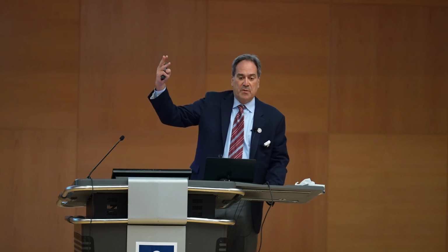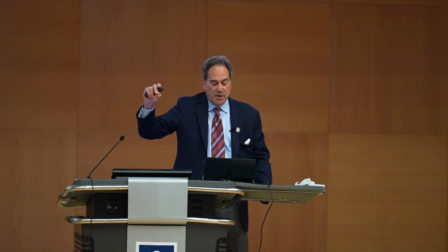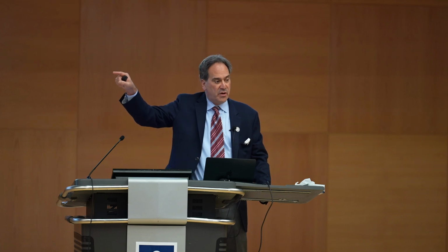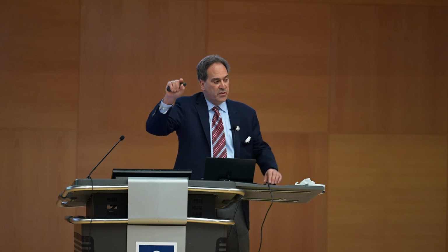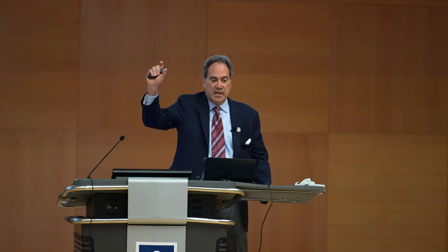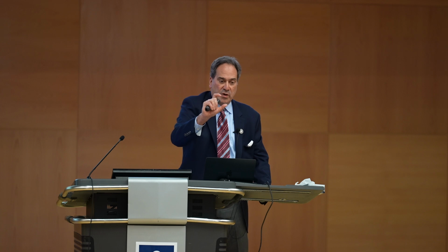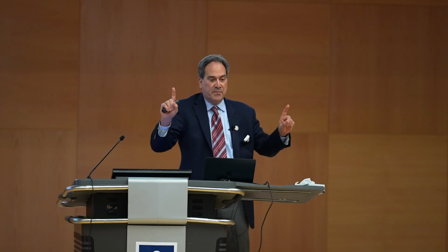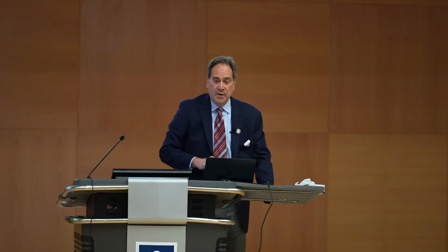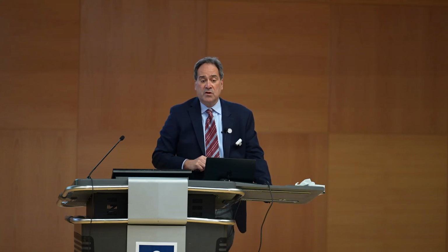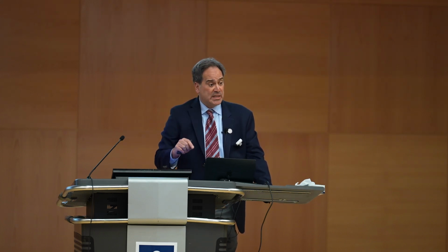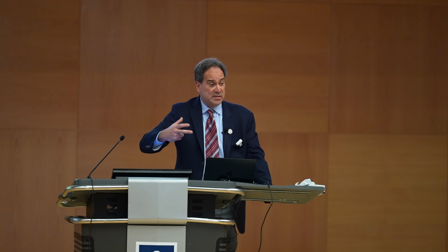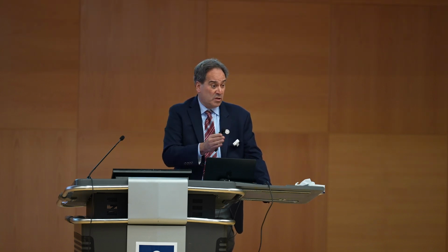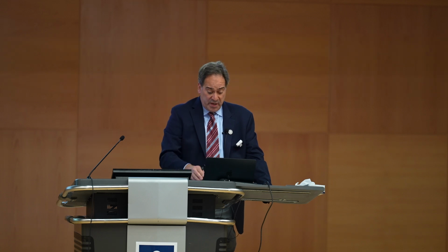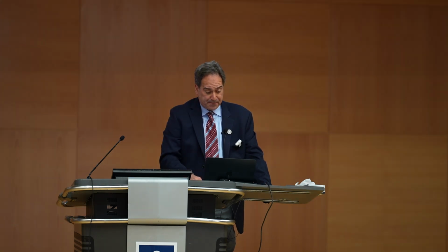These now are 3-component particles where I have gold and silver. The EDAX is giving us the color coding. That kind of orange color is the gold and silver. That's kept at a 1-to-1 ratio. The green is nickel content. And we've intentionally gone from 20% to 80% nickel content, kept the gold and silver ratio at 1-to-1. And you can see there's almost a perfect linear relationship. Okay, so that's powerful. If we're going to think about synthesizing deliberately megalibraries where we can control at least composition and size, we need to have that type of understanding.